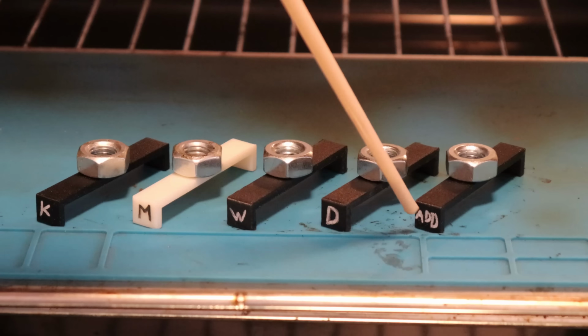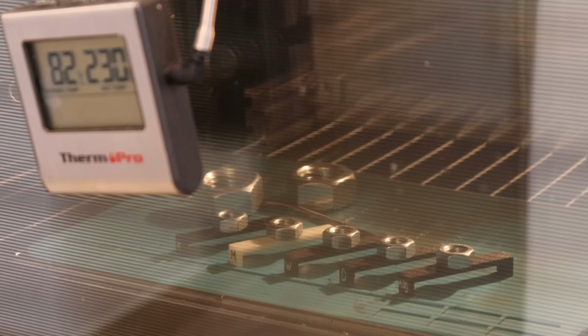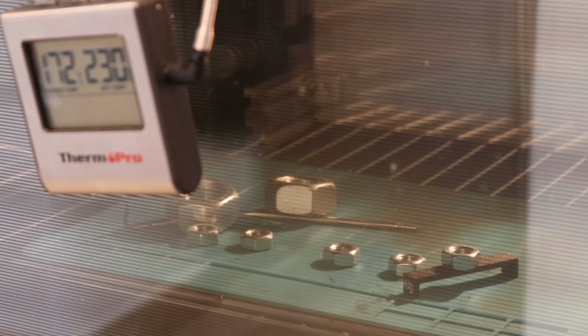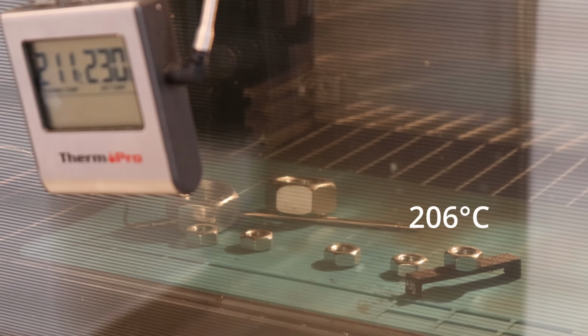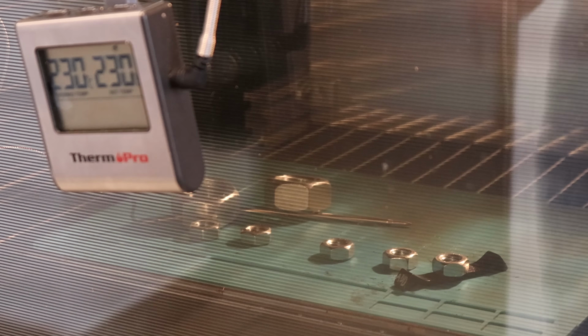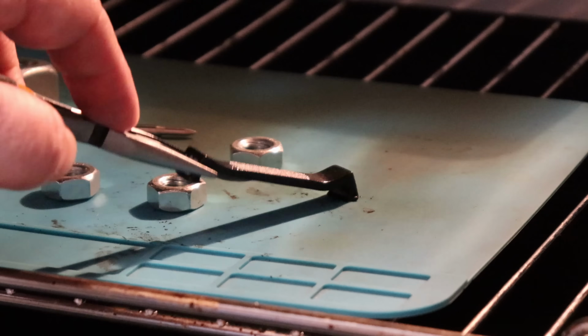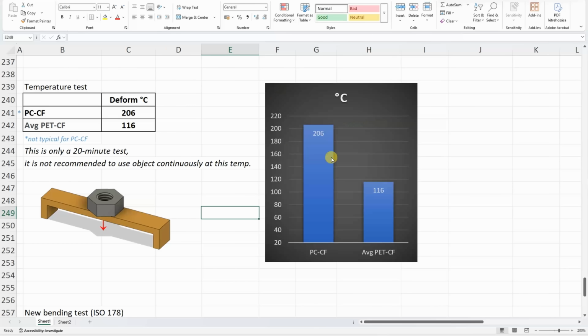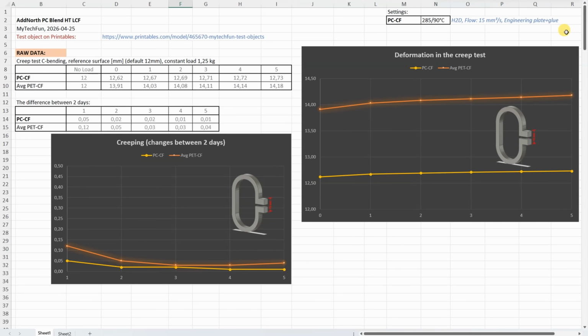Temperature test in the oven, and this is the filament from this video. And as always I have several tests in progress, and most of them deformed much earlier, so I have to take them out. And I continue with the testing with this AddNorth PCCF filament, and only at approximately 200 degrees Celsius did it start to deform, which is huge, very good for a PCCF filament. At 230 I stopped the experiment. Of course, at this point it was completely deformed and flexible. This is extremely good temperature resistance, which is not really typical for PCCF filaments. Yes, they are more heat resistant compared to the average PET-CF, but exactly this filament is almost in the range of some nylons.